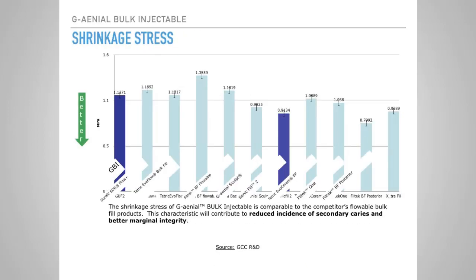Next, the shrinkage stress. This is important because it also reduces the incidence of secondary caries and gives you better marginal integrity. When you look at the G-aenial Bulk Injectable, you can see that it compares to all of the other materials on the market very, very well, and it's better than most of them. So when it comes to shrink and stress, this is a very, very good product, and it will hold up when you're talking about that capping layer. It will definitely hold up to the pressures of the occlusal force.